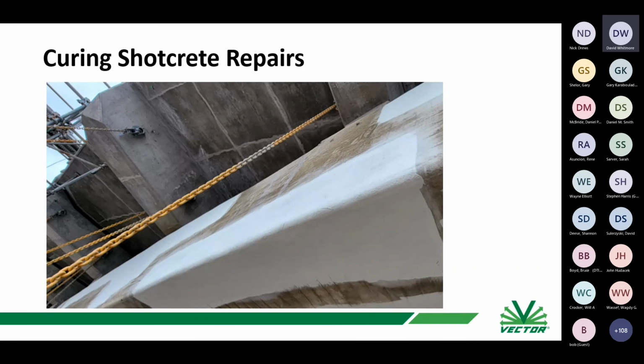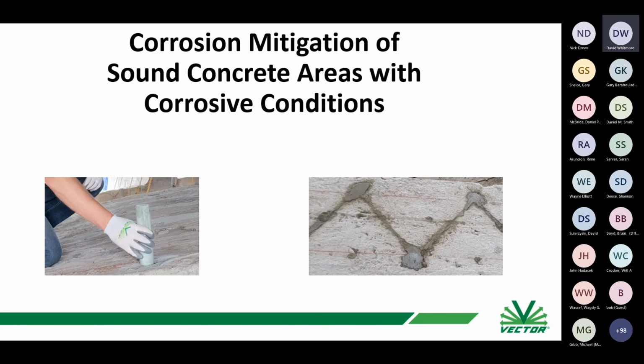After the repairs, it was mentioned already about curing. Most places they're doing wet curing, but on the underside repairs, they're basically putting one application of the actual coating that they're putting on to the concrete as basically a curing membrane. There are areas in between where the physical concrete repairs are, where they're installing these anodes in drilled holes.